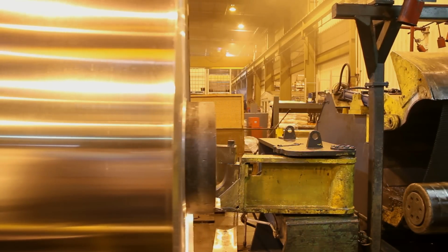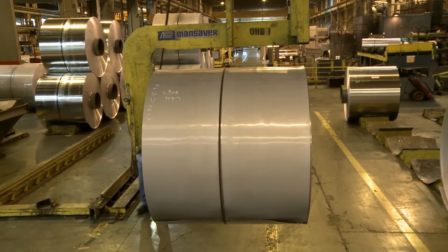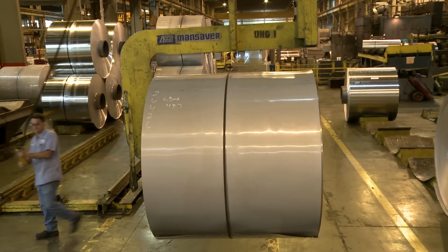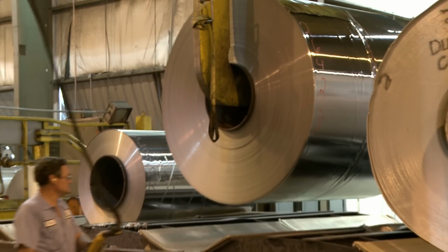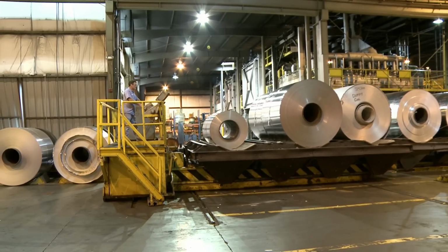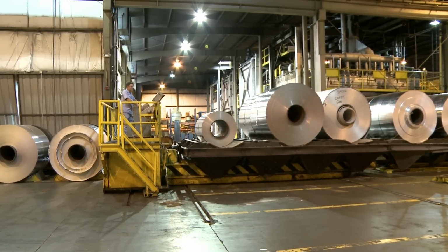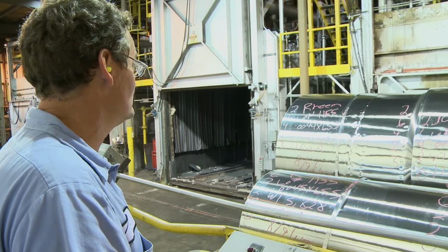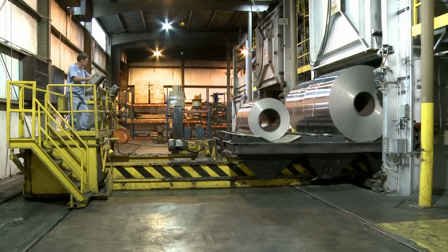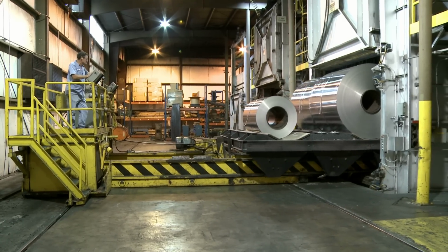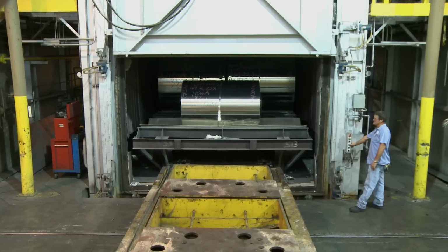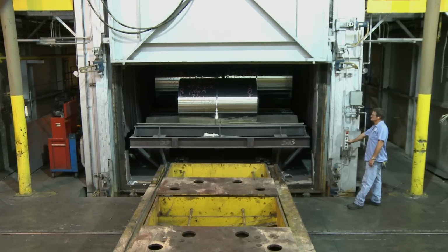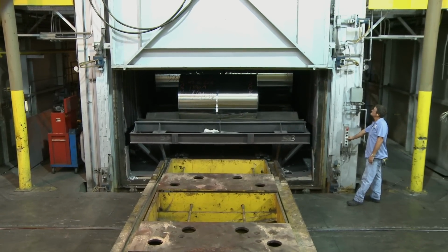After an initial pass on the cold mill, coils are brought to the annealing ovens, which soften the metal for continued reductions on the mills. We have 4 sheet annealing ovens. They have a capacity of 6 coils per oven. We can range up to 1,140 degrees during cycle. Our oven cycles vary. We have some as short as 12 hours and some go up to 30 hours.